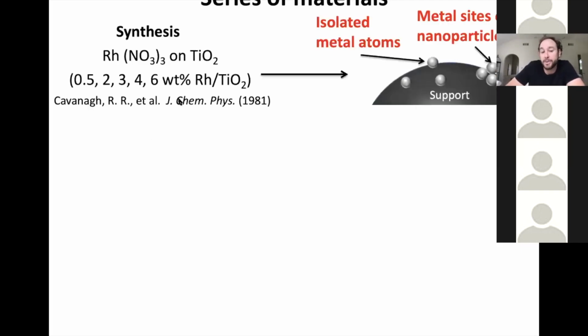So what we did is we went to the literature and looked how we could make a series of materials where we thought we were varying the ratio of single atoms of rhodium to clusters of rhodium within that material. And we found a nice paper, again from John Yates's group, who did a lot of work in this area, showing that if you simply take a nitrate rhodium precursor and do an impregnation process onto TiO2 supports, and you relatively mildly treat this with calcination and reduction processes, and you vary the weight loading from about 0.5% to 6%, that you can vary the relative populations of clusters to single atoms. And so we use this as a guide to say, let's make a series of materials and let's see if we can correlate the relative population of single atoms with the appearance of high selectivity to CO in this CO2 hydrogenation process.